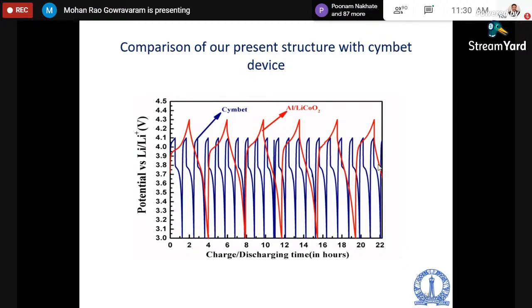The packaging that he has used, though it looks like a microelectronic packaging, is not the ideal microelectronic packaging. There are two kinds of microelectronic packaging. One is called polymer packaging, the other one is ceramic packaging. Polymer packaging is not 100% foolproof for moisture. If you want 100% foolproof moisture protection, you have to go for ceramic packaging. But the cost involved in polymer packaging and ceramic packaging differs by about 10 times. So for the initial prototype samples, he has not used ceramic packaging, he has used polymer packaging. He has mentioned it also. And that is the reason why he said after 48 hours they don't work, because moisture goes in. While putting into the pouch and sealing it, he put it in a nitrogen ambient and sent it, so that no damage will be done during transit.